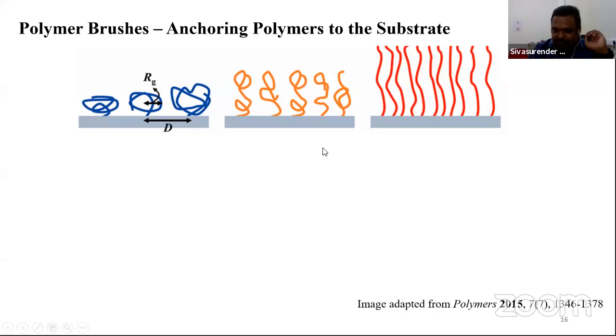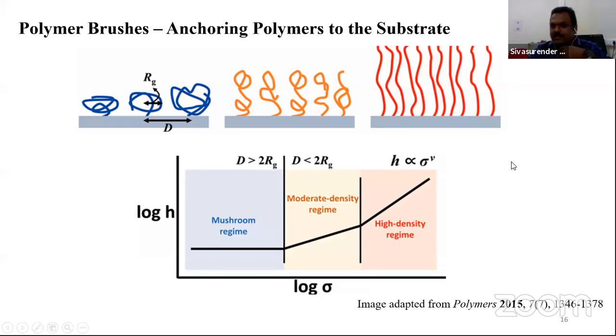Now one way of quantifying this is by looking at the height of these polymer brushes. If you increase the density of grafting, or of attaching, which I call sigma here, the grafting density or the adsorption density of chains, then at very low densities where the polymers are well separated, the height is not defined by the grafting, right? It is defined by the random walk of the polymers. The moment you start making the coils touch each other, the height starts increasing. And at very large grafting densities, it goes almost linearly.